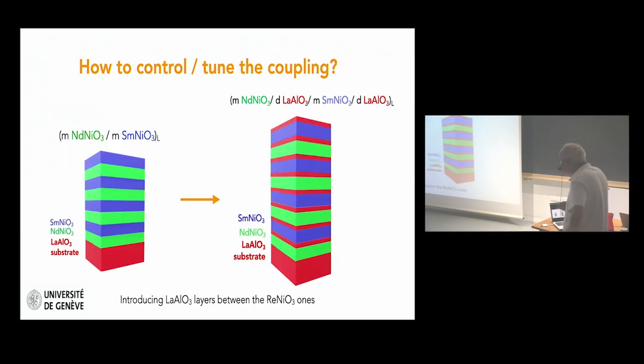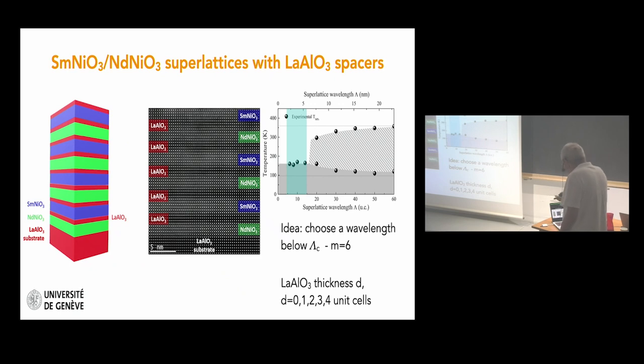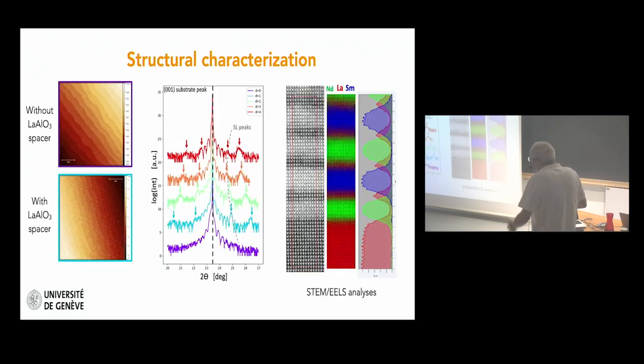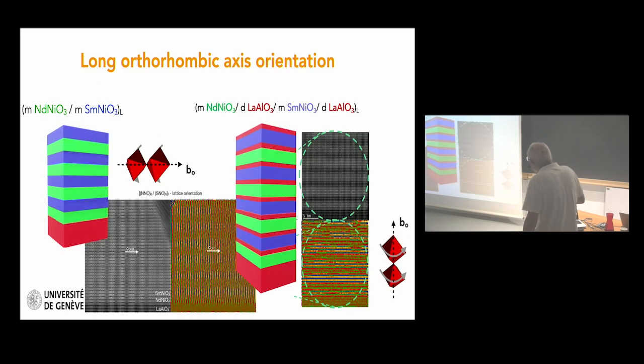Okay, so we tried to insert these lanthanum aluminate layers, and the way to go is to select a wavelength which is in this coupled region. So we chose 6 unit cells. With 6, in principle, you have a unique transition, and we put 1, 2, 3, 4 layers of lanthanum aluminate. So if you do this, samples have been realized and characterized.